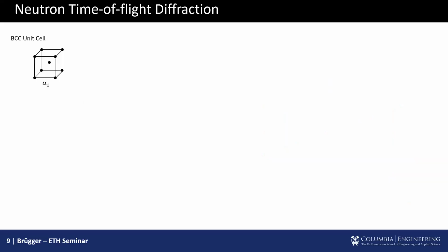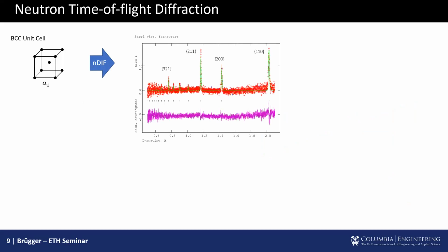So, as I've already mentioned, essentially what we do is, and if you're a structural dynamicist, it's all sort of the same thing. It's essentially just the least squares fit. But what we do is we irradiate a crystalline set of unit cells. And from that, we get what we call, in this case, this is time of flight neutron diffraction, a time of flight spectrum. And each one of these peaks is actually the delay of those neutrons by interacting with a specific atomic lattice direction in the constituent material.